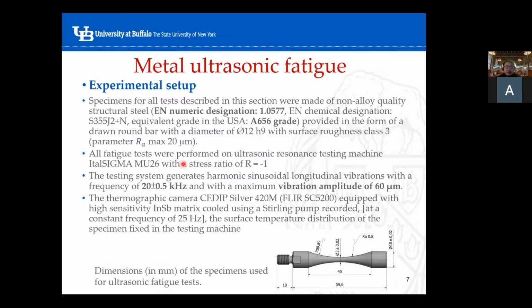Before that, I would like to quickly go over the test setup. This is our test sample, with all diameters in millimeters. You can clearly see this is a very small sample, only about 6 centimeters. This steel sample is equivalent to the A656 grade steel in the United States standard, and it has a very specific geometry. These geometries have to be designed in very specific detail so that they can create the required resonance frequency.